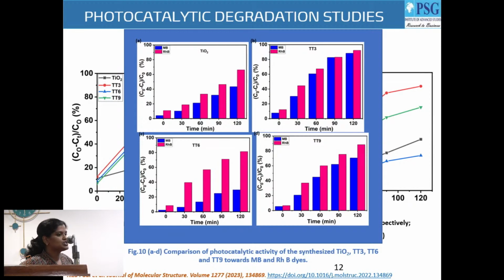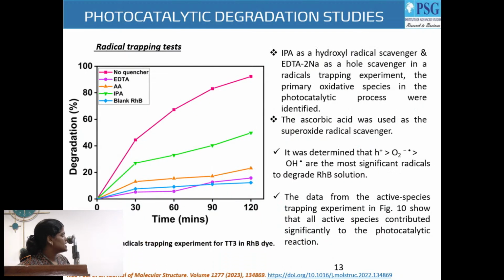And TT3 is showing 96 to 95% degradation, and we have done the scavenger test, which shows EDTA and ascorbic acid, which shows the active species are holes and then superoxide radicals, then IPA, which is for the hydroxyl radical. So my composite nanomaterial shows the presence of holes is higher.